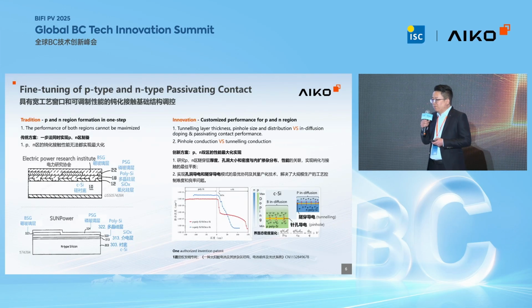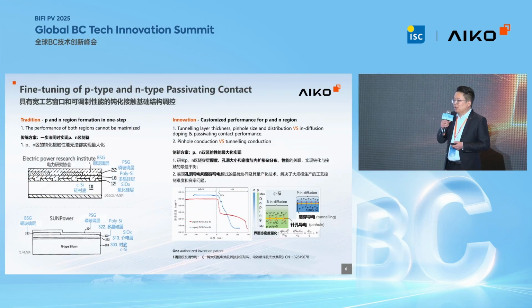So here we study the tunnel layer thickness, pinhole properties, and the in-diffusion doping layers' influence on the passivating contact performance. The pinhole conduction and the tunneling conduction in both regions are well designed and balanced. So finally, we can get the best performance for P and N regions, which is a very solid foundation for VOC above 750 millivolts.